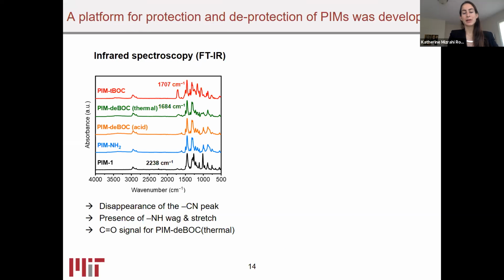So we were able to carry out all of this functionalization, and here we can see the FTIR, where for PIM1, we have the nitrile group peak that is expected. Then when we look at the amine-functionalized samples, you can see that there's the NH wag that's expected for both the regular initial amine sample as well as the deprotected ones. And finally, there's the carbonyl peak that's expected for the TBOC-functionalized PIM. And we saw that there was also one of these peaks for the thermally deprotected sample, which made us very curious to think about what changes may be happening in the oven in addition to deprotection, which is something that we look into in the next slide.